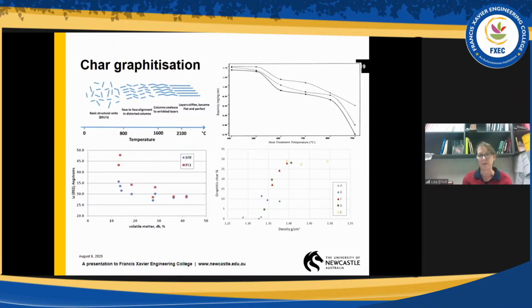You can see here, we have also the higher the temperature the char gets to, the less likely it's going to be reactive, and it's because it's become more graphitic in nature. We have two ways of measuring the graphitic nature of the char. One is to actually measure the crystalline structures that are formed. We do that using an XRD. So you can measure LC and LA.